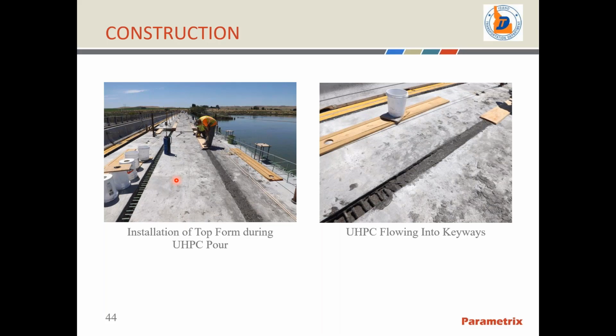In fact, it actually flows up and out of the form, especially in low spots. So pre-stressed girders tend to camber up, and so the ends of the girders would be the low spots, and this material really would start to flow out of it. Plus, the specifications for the project required that the UHPC flow about 1/4 of an inch up out of the joint, and then the contractor has to grind the joint flush with the deck after it's cured. So in this picture, you see the crews installing the forms across the top over that. And then in this picture, you can see the material flowing as it is being placed.